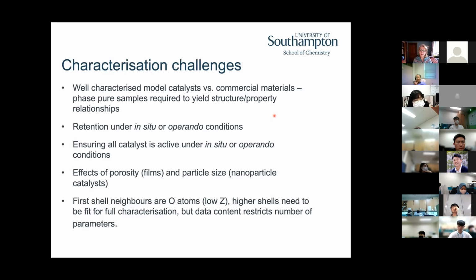We want a thick enough or loaded enough electrode that we get a good X-ray absorption spectrum, so we're getting good signal to noise. But if it's too thick, then maybe not all the material is going to be active. So if I have a very thin electrode, a thin catalyst layer, then I might think that all of those atoms of the catalyst are going to be active. As I make it thicker, then I'm going to have to worry about where my interface is with my electrolyte. Okay? And so it's always a compromise.